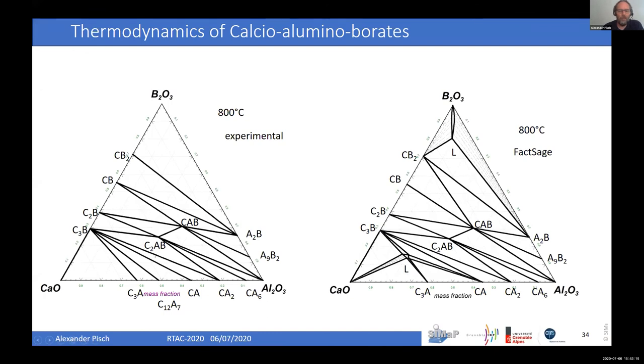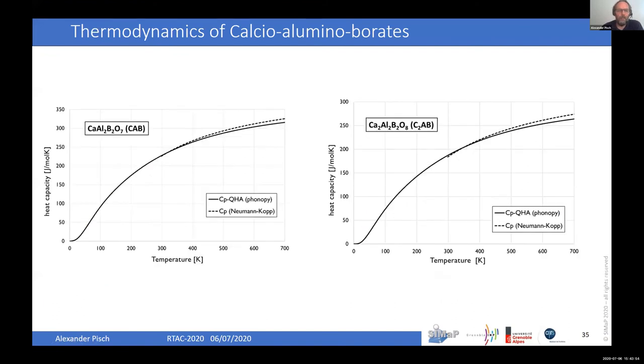So as I said before, on the left side, you see the isothermal section from the experiments at 800 degrees Celsius. On the right side, you see one calculated from the FactSage database. And overall, the two compounds are there, but what you see is a really strange low temperature eutectic on the lime-rich side. And we said it's not possible because the starting point of this study was to work with this system in building material sectors of really lime-rich. And we said, if you want to have something correct, we cannot leave this low temperature eutectic. It must be an artifact of the modeling. So we did the calculation.